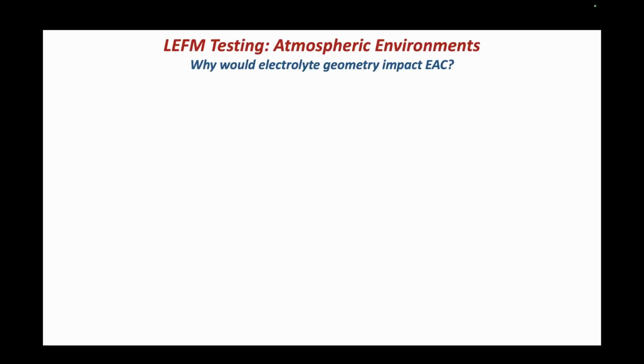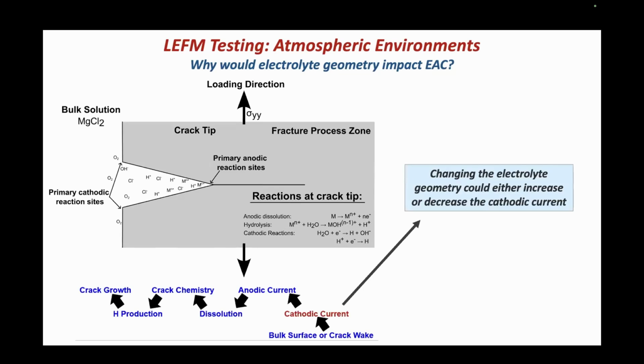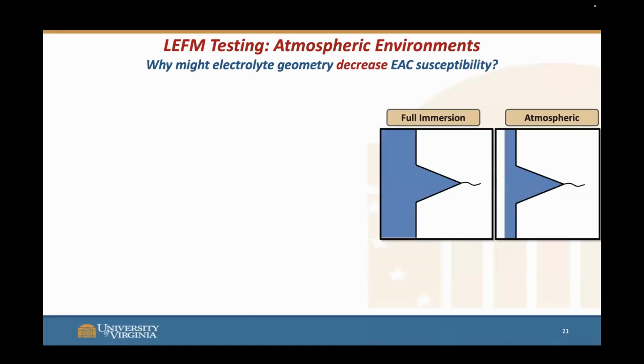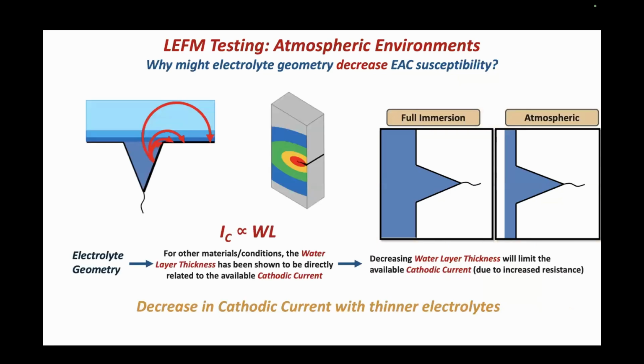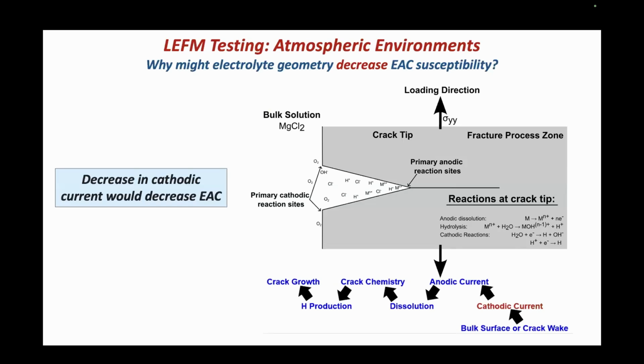So why would electrolyte geometry impact stress corrosion cracking? When it comes to the electrolyte geometry, changing the electrolyte geometry could either increase or decrease that cathodic current. And so this cathodic current will then affect our overall crack growth rate. So what might cause that cathodic current to decrease and then decrease our EAC susceptibility between atmospheric and full immersion? One of the things is that water layer thickness from other material and conditions has been shown to be directly correlated to the available cathodic current as well as the size of the cathodic current. So decreasing that water layer thickness with going from full immersion to a misting environment could limit the available cathodic current. And then this will cause a decrease in our EAC if we decrease that cathodic current with that decreasing water layer thickness